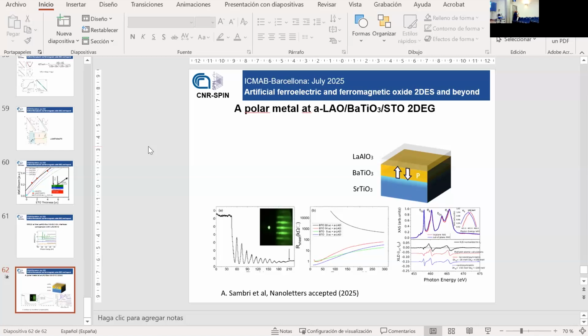What I can tell you is that step edges have an influence. Usually, if you grow this material on substrates with a very high vicinal cut, with many step edges, you get an anisotropic transport just because of the step edges.